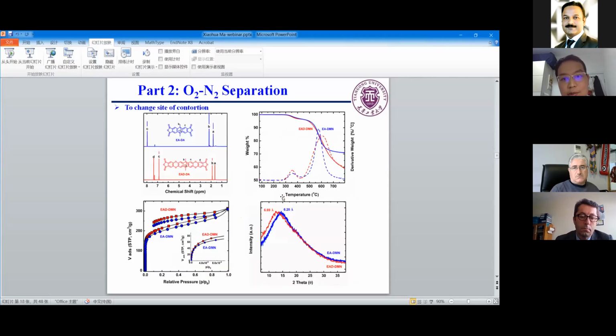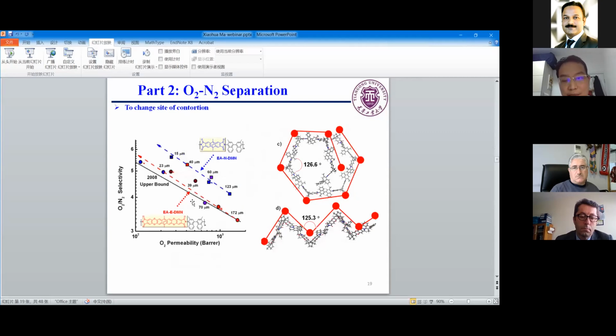The result turned out that it follows our design, and this is the extended one. The d-spacing is larger than the non-extended one, and we found their separation performance for O2/N2. The chain was longer. This polymer with